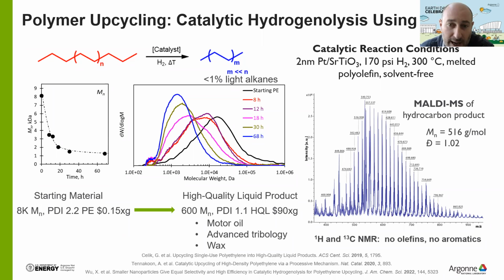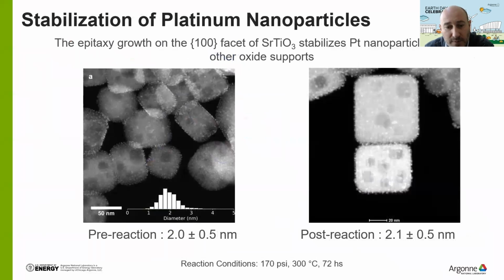And we are really trying to understand more why this particular catalyst produces a small amount of byproducts. As I mentioned before, we chose the strontium titanate because we want to stabilize the platinum nanoparticle under a very harsh condition, hydrogen and high temperature. On the left, you see the starting material, and this is after 72 hours, 300 degrees, under 170 psi of hydrogen. You can see that there are a couple of big chunks of nanoparticle, also in the starting material, but the average nanoparticle size doesn't change drastically. We go from 2 to 2.1. And this is quite interesting and quite remarkable.